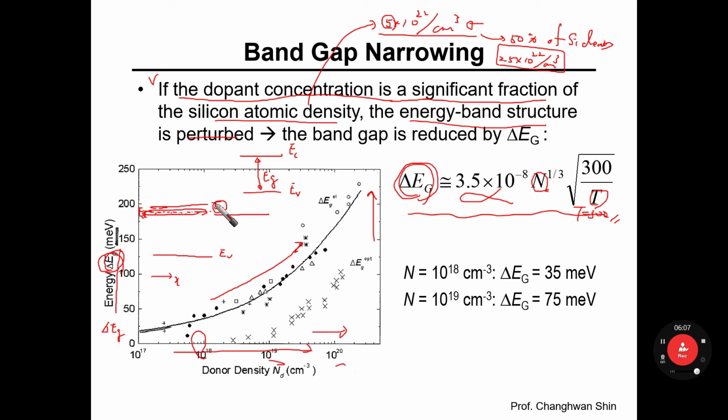The original conduction band edge is E sub C here. However, the real or working effective conduction band edge would be very close to, or match, the donor's energy level. So E C minus E D, what was it? Ionization energy of dopant atoms, right? A few tens of milli electron volts, say 50 milli electron volts. This number gets lost when we estimate the band gap energy.